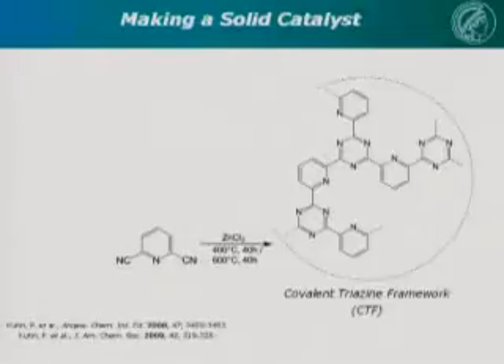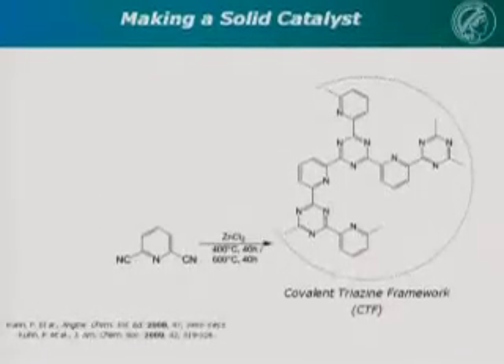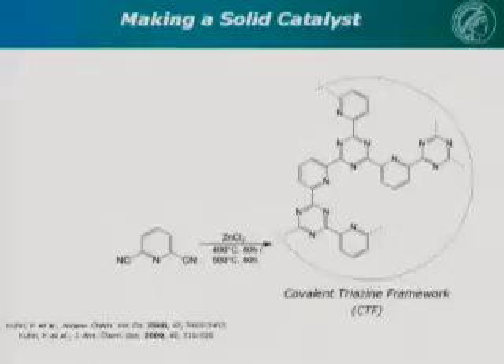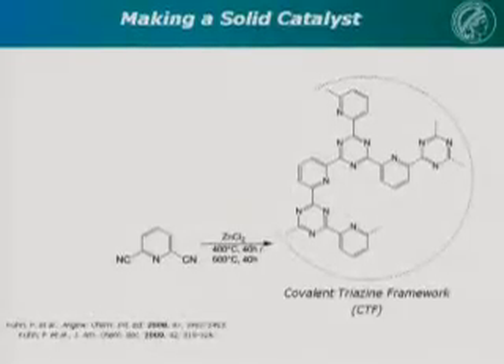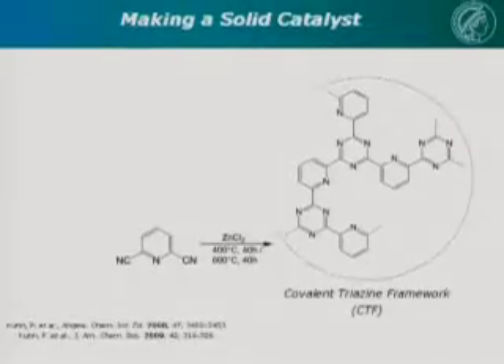We were helped actually by a publication I saw in 2008 from Markus Antonietti's group, and they had described the so-called covalent triazine framework, which you get essentially by polymerization of a dicyanopyridine under quite harsh conditions. Then you get a highly porous network, which looks like this. Markus has drawn it in a very regular way at that time, and I'm very grateful for it because otherwise I'd never have recognized that this almost looks like the bipyrimidyl ligand of the Periana system.